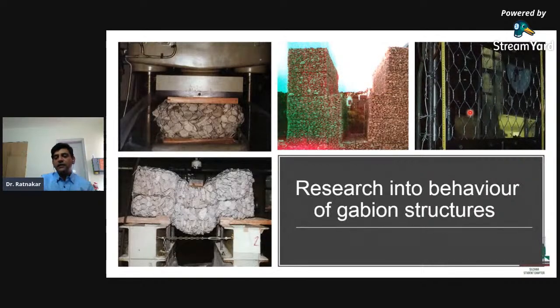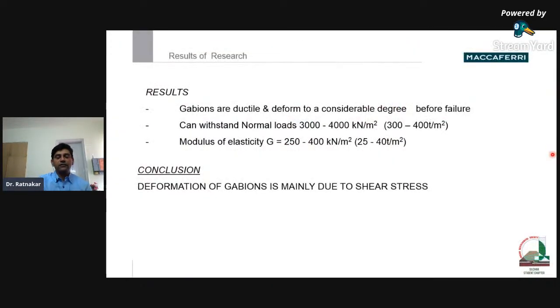In addition to that, tests on the mesh were performed, like the tensile strength of mesh, holding the mesh in a UTM and doing a tensile test. Then the tensile strength of the wire itself was tested, and the punch strength of the mesh was tested. So the results showed that gabions are ductile. They are not brittle. They deform. They give you enough indication before failure.